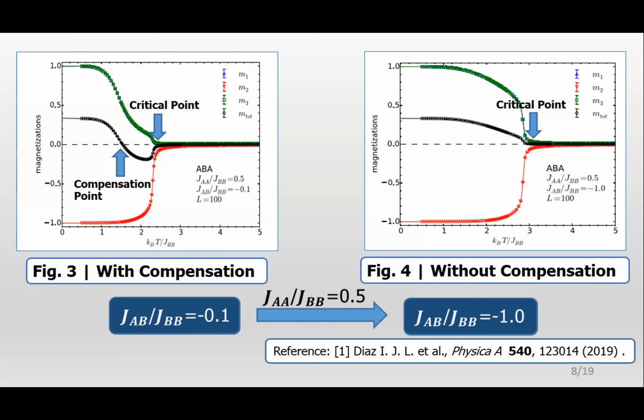When we increase the antiferromagnetic coupling ratio to 1.0, so basically there would be a negative sign before 1.0 as it is the antiferromagnetic coupling ratio, the strength is increased, whereas the absolute value in the traditional mathematical nomenclature is basically decreased. So the compensation point actually disappears. In figure 4, we find that compensation basically depends on the values of the individual coupling ratios, that is JAA by JBB and JAB by JBB. So a suitable choice is actually necessary to find the compensation point in such a system.